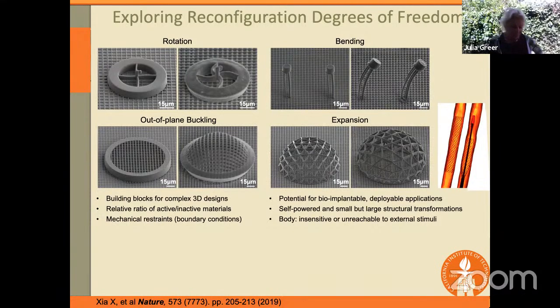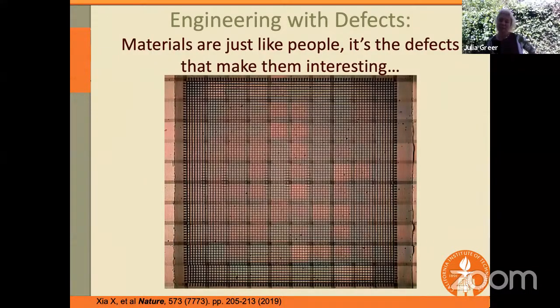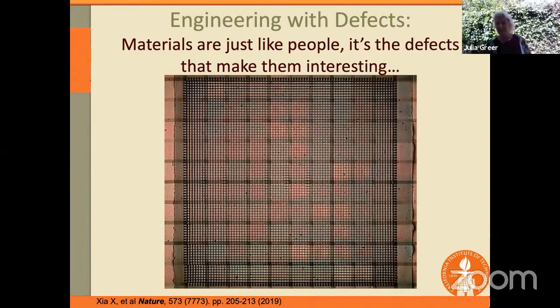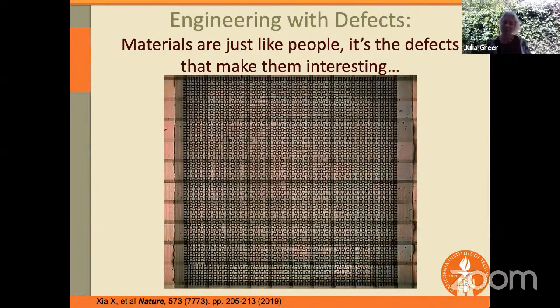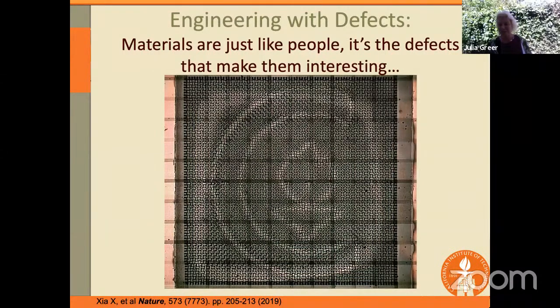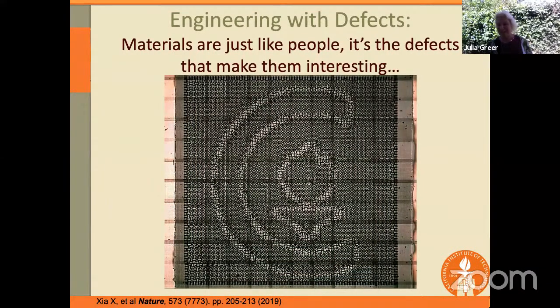And what I'm about to show you here is this. We pre-programmed a defect in here that you don't know about. And you're looking at the top view of this battery and we're about to lithiate it. And as we're lithiating it, you're going to see a pattern start to emerge. And so here's the pattern that's emerging here. And hopefully you can see right away the resemblance between the pattern that's forming in the video and the little logo that I'm showing you on the right. And so what that tells us is that once we understand the behavior of the defect, we can use this to tailor in a specific file.